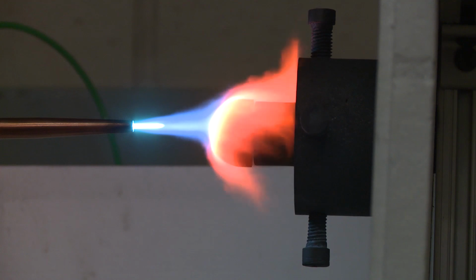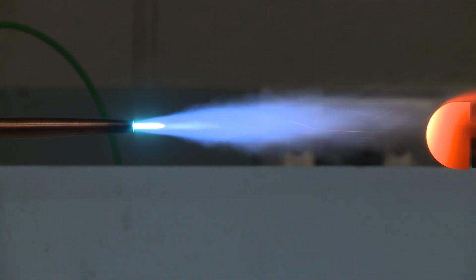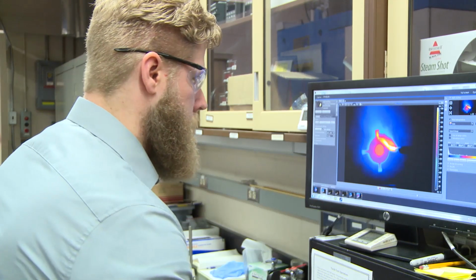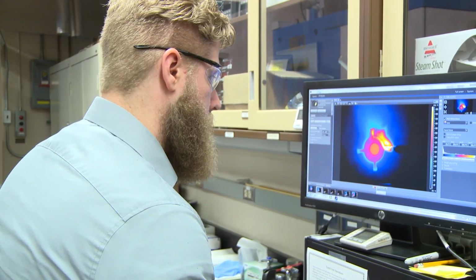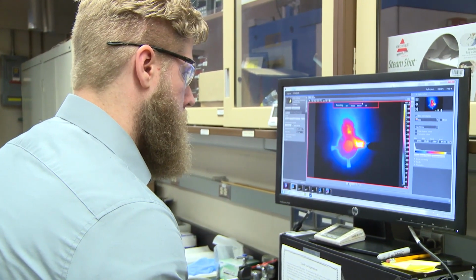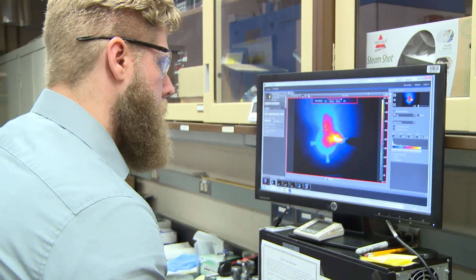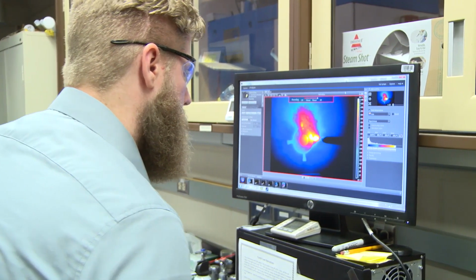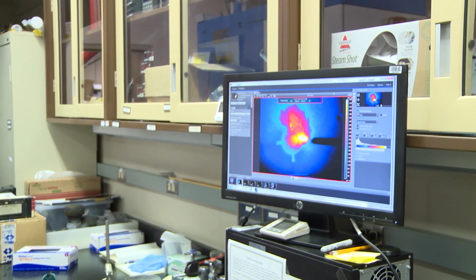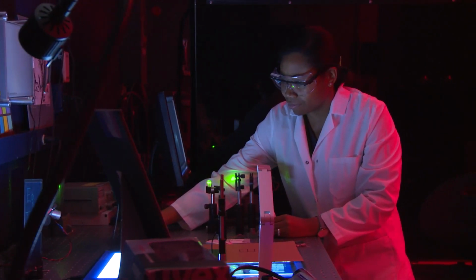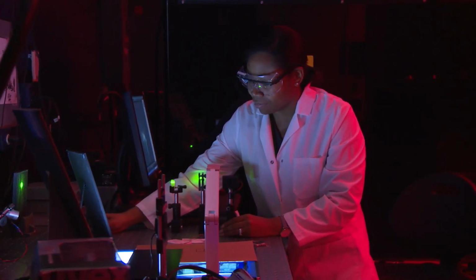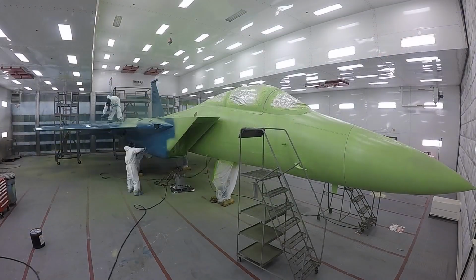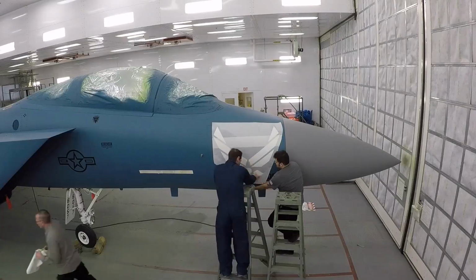Finally, we have been developing collaborations with other hypersonic testing groups to put our coatings through the rigors of equivalence to the environment experienced during hypersonic flight. We are looking for torch or laser testing to expose our coated substrates to temperatures approaching 2000 degrees C and heat fluxes of 500 watts per square centimeter. We will then extensively compare them to the uncoated substrates which experience the same exposure. This will give us a very good comparison of the robustness, oxidation, and thermal resistance of our coating system.